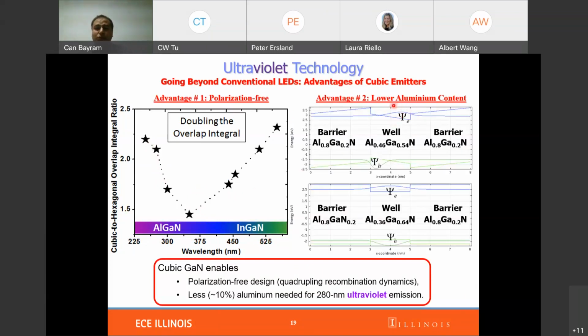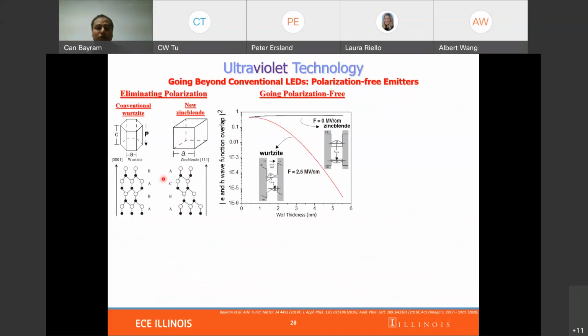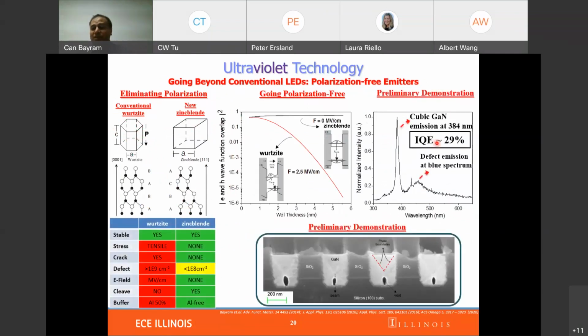And by proper design, you can lower the needed aluminum as well as needed indium content in these different spectrums. So overall, going from a 6-fold symmetry Wurtzite structure to zinc blende really increases our overall recombination dynamics and efficiency. So we recently demonstrated about 29% internal quantum efficiency in these structures that are stable and they are virtually stress-free, crack-free, and low defect density and no electric field with cleaving layer.